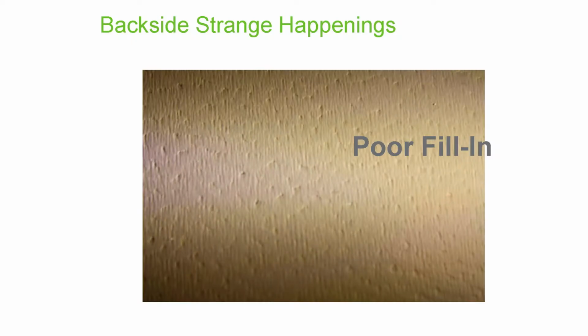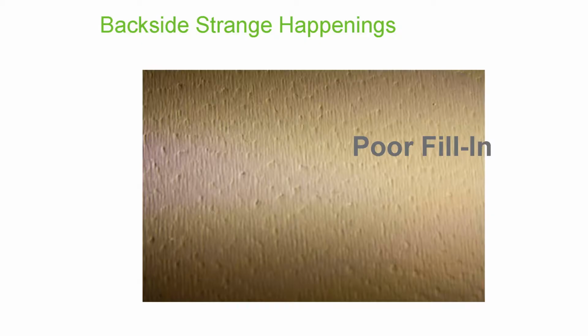You mentioned surface contamination is maybe one of your biggest problems. One of our biggest problems is mill finish. So we actually have these nooks and crannies, sort of like an English muffin, and the coater's attitude is your paint has to fill that in. Sometimes you can do it and sometimes you can't. So here's a good example of paint that is simply not filling in the gap as well as it could. Now, in this particular case, it's the backside. The backside is put on here at about 10 microns, so fairly thin film, and it may have a micron or two of primer.